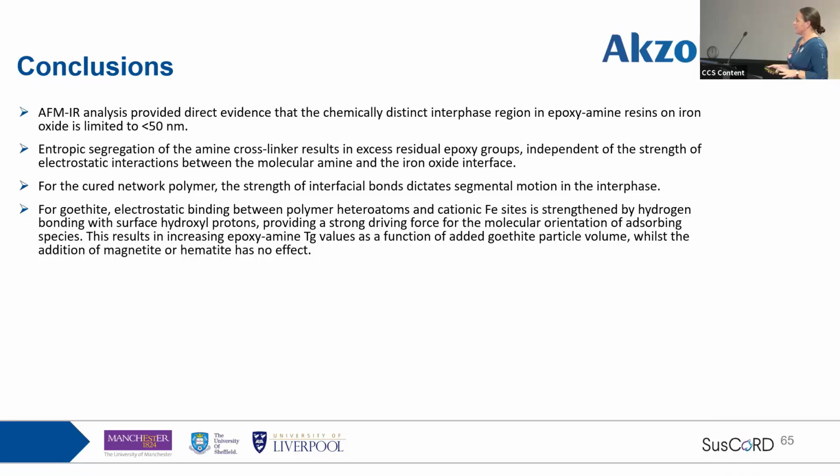For the cured network polymer, the strength of interfacial bonds dictates segmental motion in the interface. So that's a very separate effect. And we've identified, we think, these very site-specific electrostatic binding interactions that are very strong on the surface of Goethite.